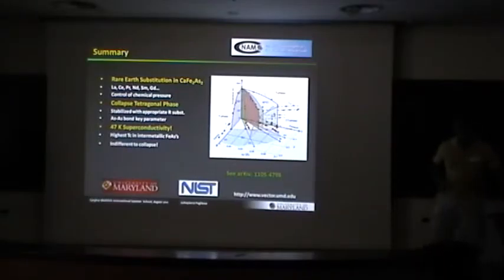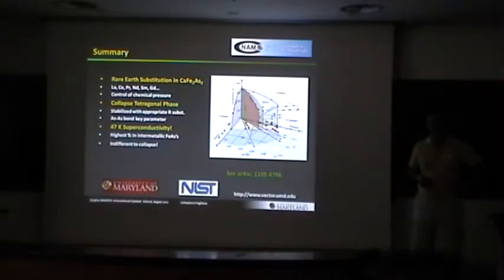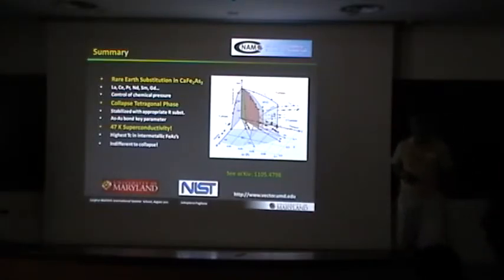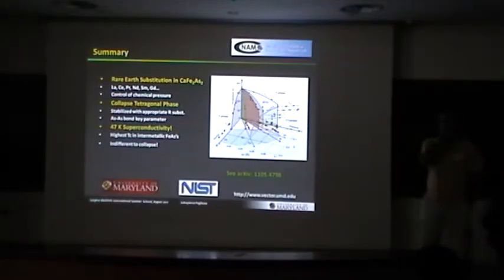So I think I missed your motivation for doing this. It's very interesting, of course, and it's great, fascinating results. But the initial experiments on the collapse on the calcium material showed that the superconductivity was there only in the stressed phase, right? And now you're trying to essentially, I would imagine, reproduce some kind of analog of the hydrostatic pressure, right? Uniform chemical pressure. Yeah. And that would be no superconductivity. Yet you get 47 Kelvin, so what's this connection?